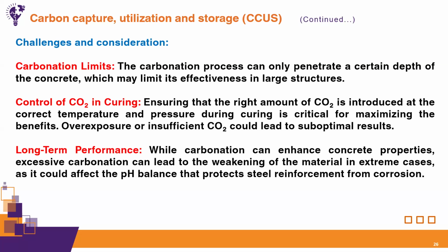The second limitation is the control of carbon in curing. Ensuring that the right amount of carbon dioxide is introduced at the correct temperature and pressure during curing is critical for maximizing the benefit. Overexposure or insufficient carbon could lead to negative results. So that's why it is very important to optimize the carbon amount, the temperature, and the pressures at which this carbon can be inserted or used for curing purposes. So it is very important to optimize all these parameters when carbon is used as a curing agent.